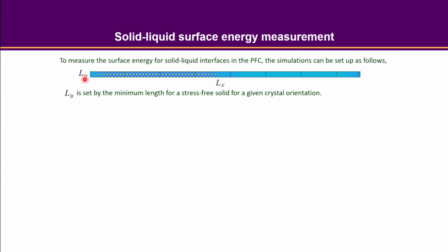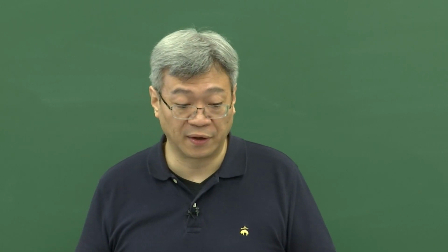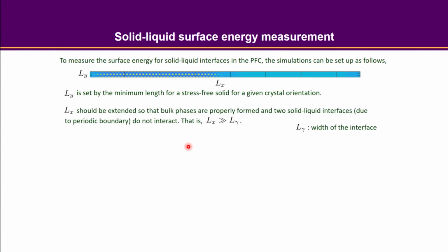But on the contrary, you don't have to worry about the periodicity in the x direction, because it's a solid-liquid interface. So the solid is not coming back to the other end. So the geometric constraint for this kind of system is less. Usually you can really try out several different orientations, because the only thing you care about is probably to set up your simulation with several Ly. They are not large, but you don't really have the other constraint in the x dimension, right? So that's the system setup you could have for the solid-liquid interfacial property, all right?